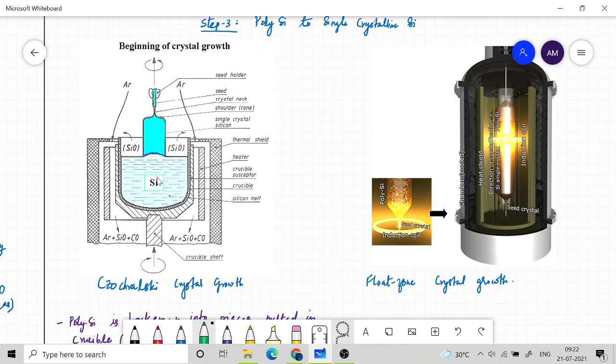Okay, so this is basically a diffusion mechanism where these impurities are getting into the solid crystalline structure and taking active positions. Okay, so active position means replacing the silicon atom and taking its place. Then only it is treated as electronically active.